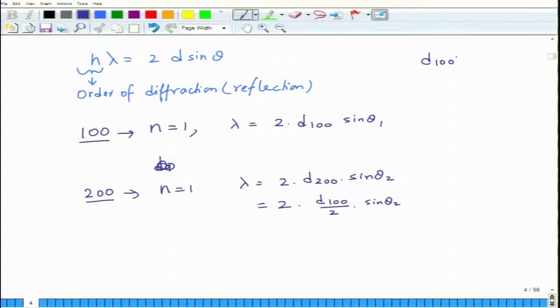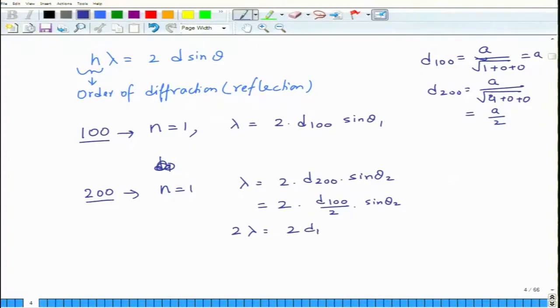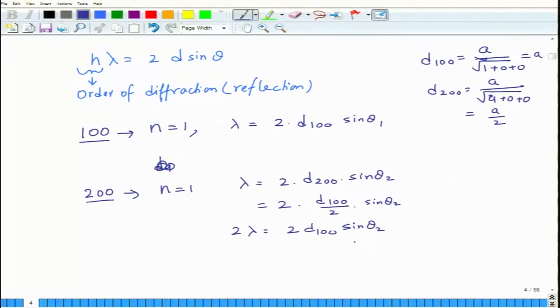Because d100 is A divided by square root of 1 plus 0 plus 0, and d200 is A divided by square root of 4 plus 0 plus 0. Okay? So, you can see that d200 is half of d100. So, this becomes 2 lambda is equal to 2d100 sin theta 2. So, basically it means a 200 peak, the diffraction peak from 200 plane, is nothing but second order 100 reflection or diffraction peak.